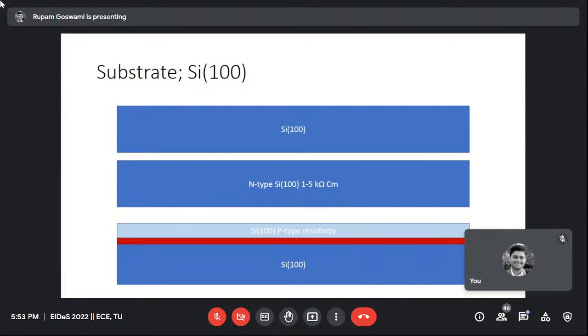In the other cases, the resistivity value and its uniformity over the entire wafer area is questionable, because wafer size is always increasing. So how can we make a uniform resistance over the whole surface? It is questionable in the above cases, but in the SOI case it will be ensured, and this is the reason. But the cost of the substrate is quite high. It cannot be a low-cost process, though the process steps are not crucial. But still, if you have an active layer thicker than what you require, suppose we want a 1 micron thick active layer and it is 2 micron, and we want to reduce it,